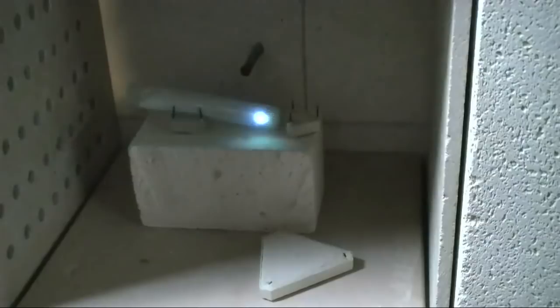I set it up in the kiln and set the kiln to 800 degrees for two hours. When I came back, I shined my violet laser on it and it was still glowing green, but very short persistence, which was very promising.